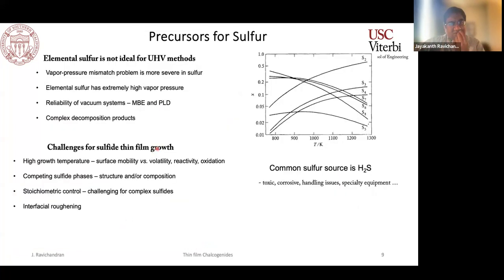So some issues when you're trying to grow these materials using conventional vapor phase high vacuum type techniques is the precursor for sulfur. It's an important choice one has to make, and how do you want to go about it? The most simple choice of precursor here would be elemental sulfur or molecular sulfur, if you want to think about it that way, and it has extremely high vapor pressure.